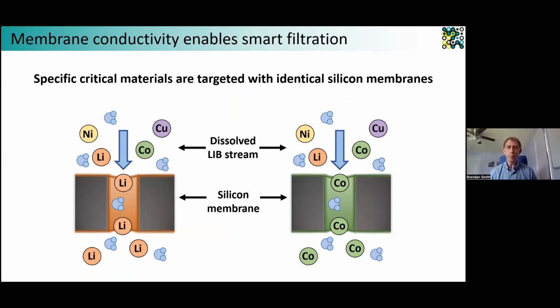Here's a very simplified example of how that actually looks, and I'll show some images on the forthcoming slides. So here we have a cross-section of the silicon membrane. It could be the same membrane in both cases, the exact same pore structure and pore size, et cetera. What we do is just by turning a knob that would change the voltage or current conditions flowing into that membrane, we can very selectively extract a very specific material.